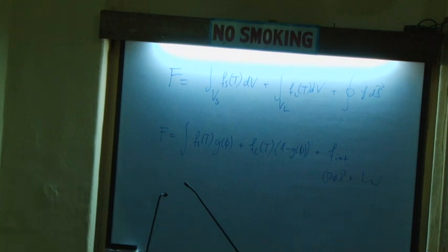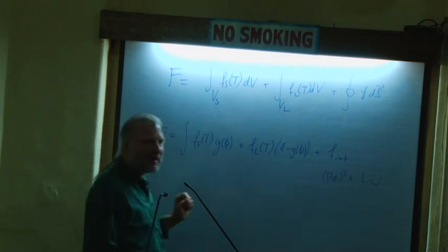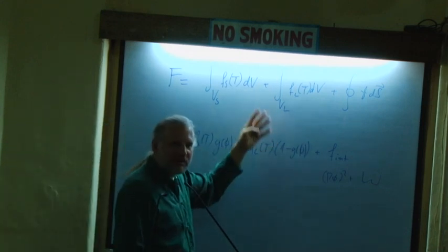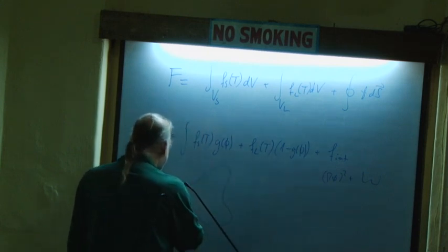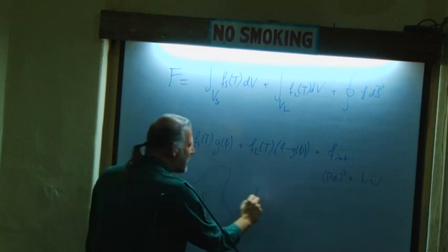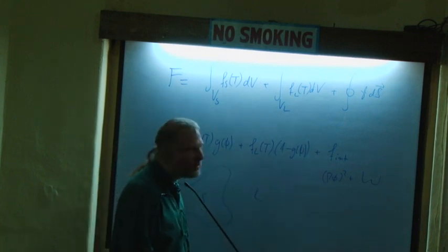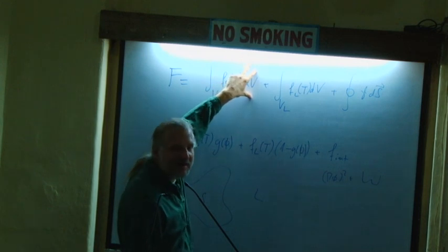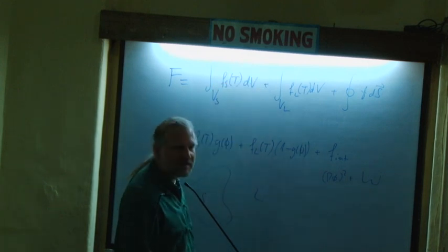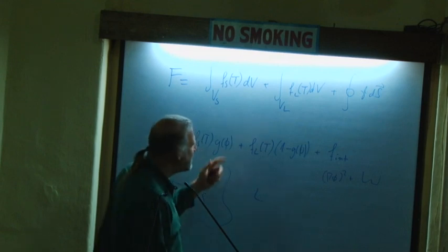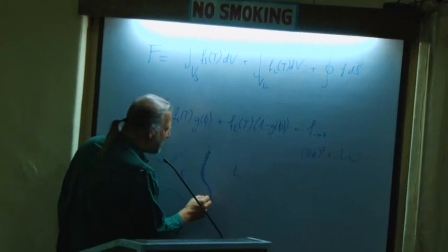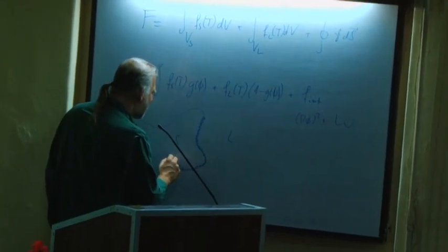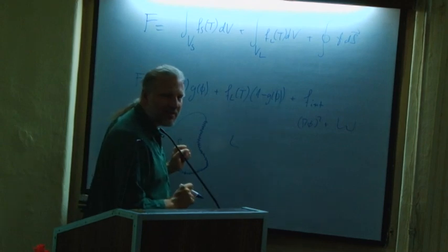and I will get exactly this interpolation for the entropy that I have written down here. Okay? And this is particularly interesting because what is the sort of hand-waving interpretation for this expression? Suppose that I have my solid crystal and my liquid in the sharp interface representation. Then my free energy is given by this expression. Now if you stare at this, actually what this is, is that I smear out this surface by replacing the mathematical line with this phase field profile.